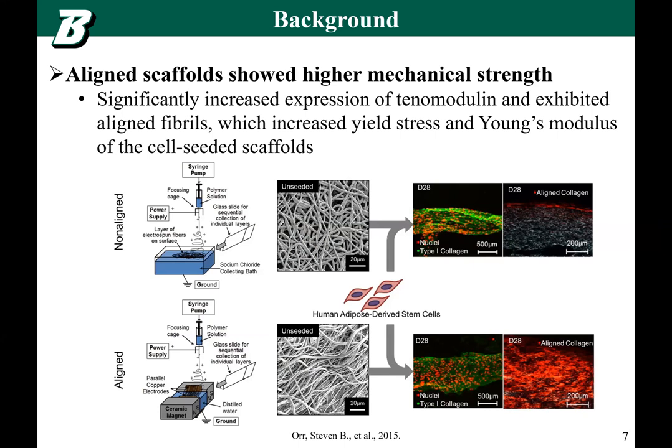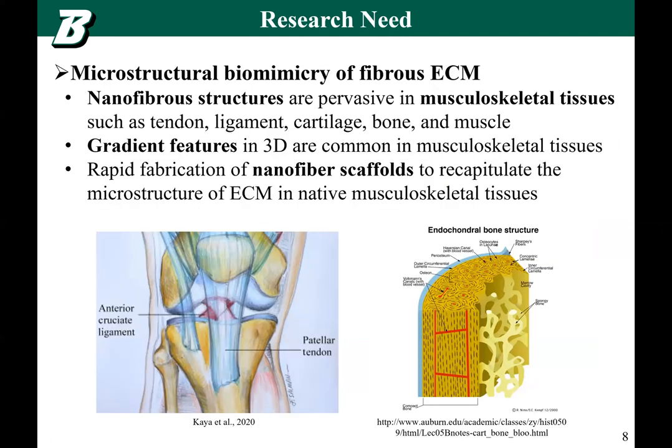In this research, it shows a significant increase in expression of tenomodulin and exhibited aligned fibrils, which increased yield stress and Young's modulus of the cell-seeded scaffolds. So as you can see, not only can the mechanical strength of the scaffold be enhanced, the cell-seeded scaffold will also have improved mechanical strength. And now that we know that aligned fibers can mimic the native fibrous tissues, and they are very beneficial for cell